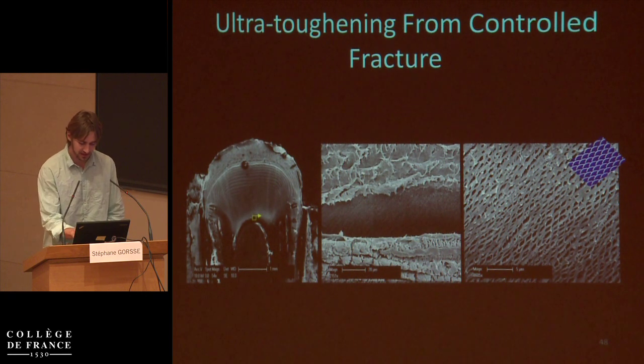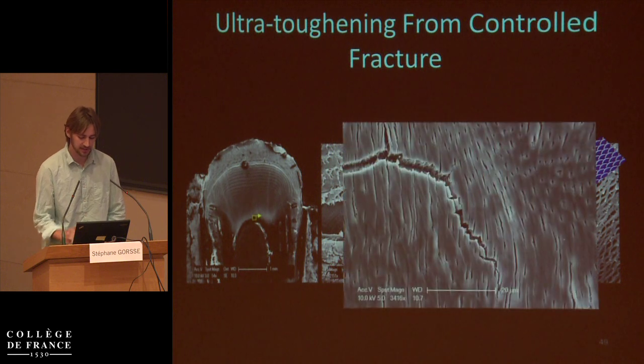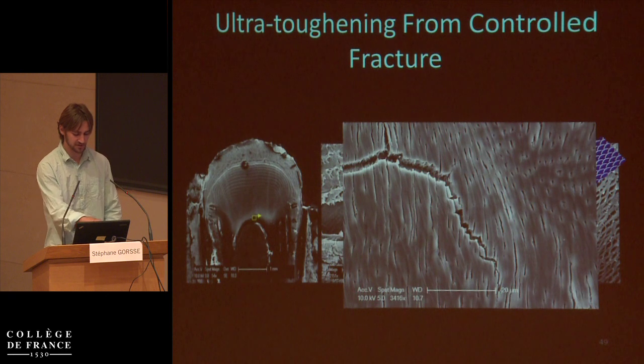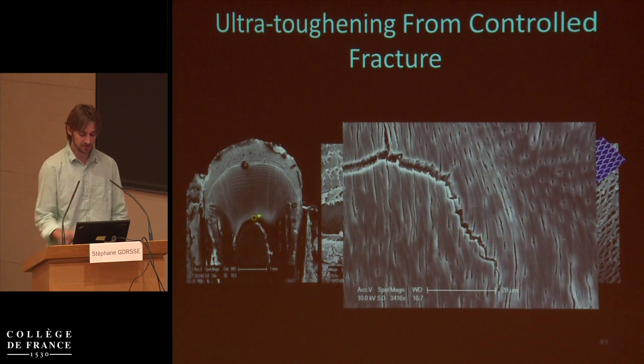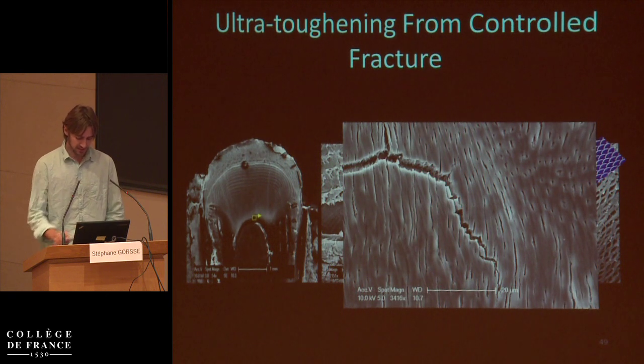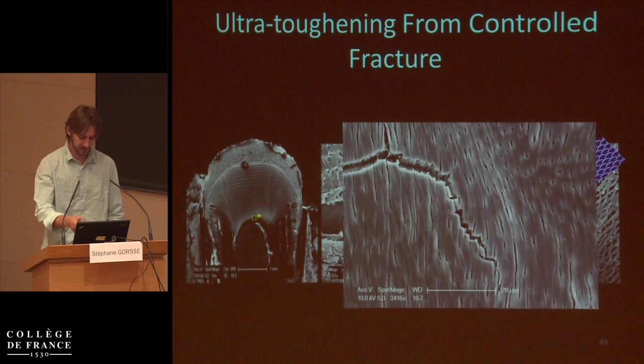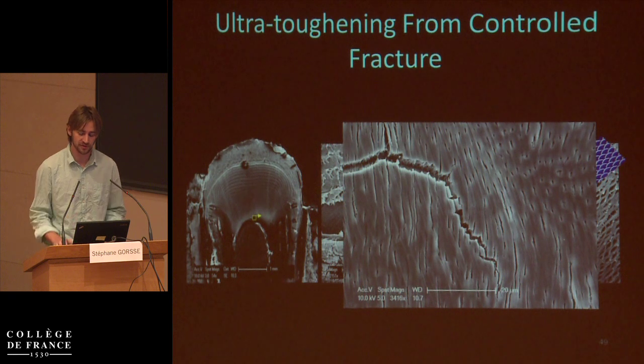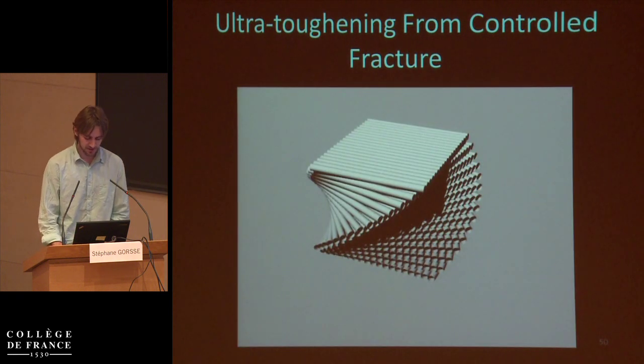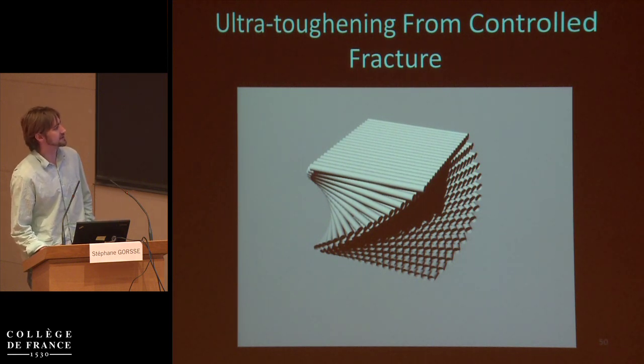And it's certainly a lot easier to see when you demineralize, but if you ion polish, in this case, this is transverse, so this is parallel to this first picture, then you see these microporous channels, and we ion polish because typical polishing would fill these porous channels in with material, with the abraded material. So now I'll try and take some time to really detail why it is that these two effects synergize.